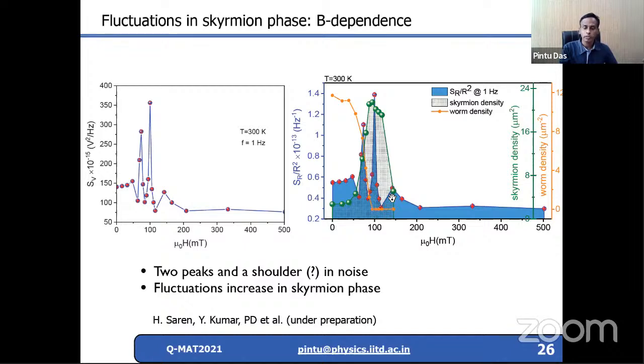And you see that on the right hand side at around 150 millitesla, there is a hump, a shoulder kind of feature in the noise again. So this is also not very clear. As I said, we are trying to understand the data. So overall, I would like you to note that in general, the fluctuation is increasing. The low frequency fluctuation in the dynamics is increasing in the skyrmion phase.